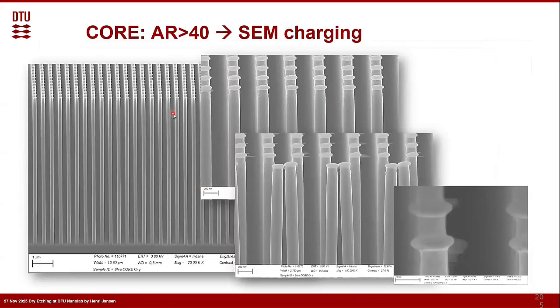But if you go beyond aspect ratio 40, we can already see some problems while we're looking in the SEM. The structures, these pillars, are so slender that while you are looking with the SEM, they start to vibrate. The charge from the electron beam while scanning is charging one of them, but then it's attracted to the other one, or repelled from the other one, and therefore it touches the other one. It's even possible that they start to touch and merge. They click together and don't come apart anymore.